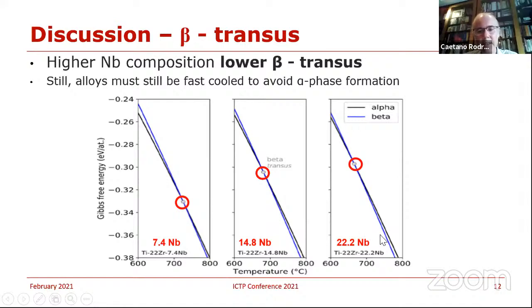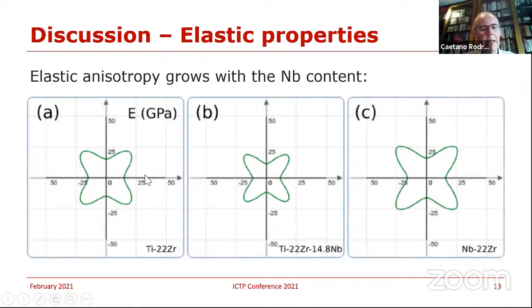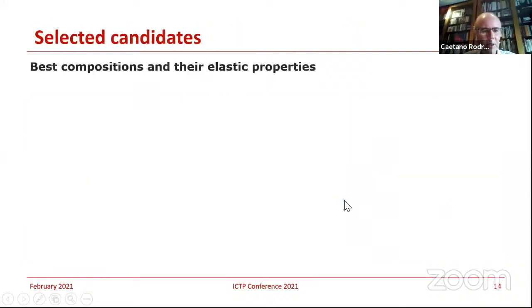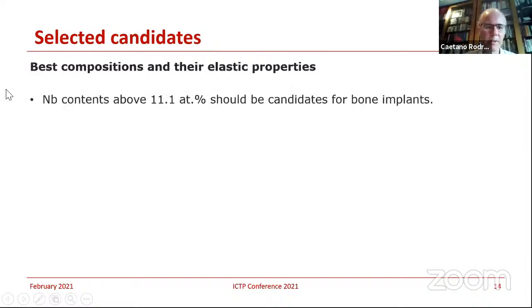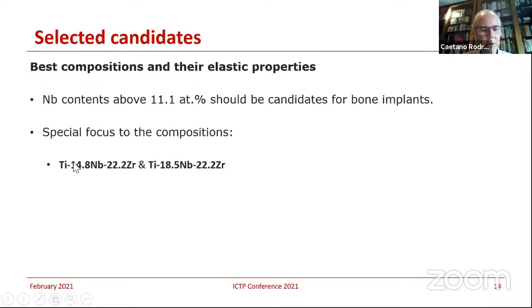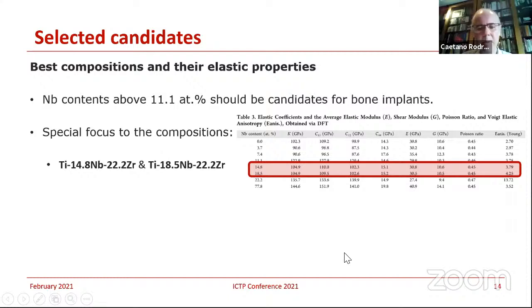As well, you have to see how is the elastic property. So here I'm going to show you two-dimensional information for the elastic moduli with increasing niobium content. In summary, I can give more detail later, but in summary, you could get a best composition based on the elastic properties. So basically, the information is that for the contents with niobium above 11, you have good candidates for the bone implants. You figure out the special compositions, and you calculate the full elastic properties of that.